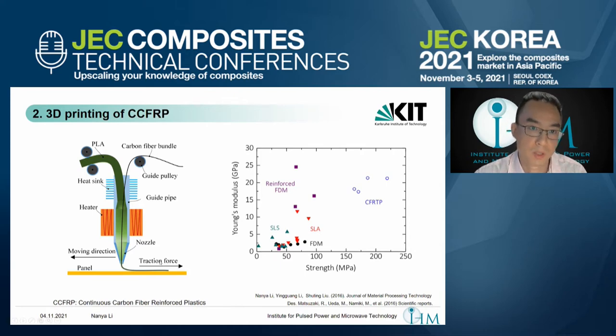If we can optimize the printing process — such as the printing temperatures or the gap between the printing nozzle and the platform — by adjusting these parameters it becomes possible to adjust the compaction degree of the printed parts. Based on current research, it is possible for printed parts to reach nearly the same Young's modulus as conventional CFRTP parts.